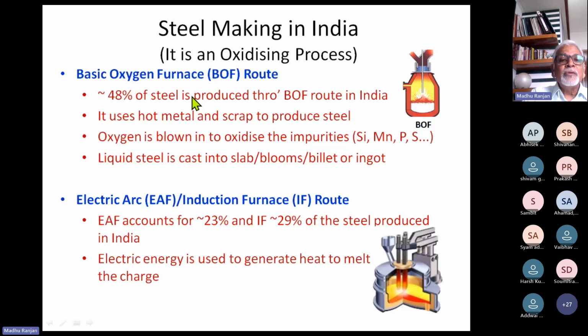Steel making route: about half of the steel made in India is through the basic oxygen furnace route. Here the hot metal from the blast furnace is charged, and some amount of scrap is also charged as a coolant. Oxygen is blown into the converter, where the impurities such as silicon, manganese, phosphorus, sulfur, etc., get oxidized and go into the slag. The resulting liquid steel is cast into various shapes like slab, bloom, billets, or ingots.